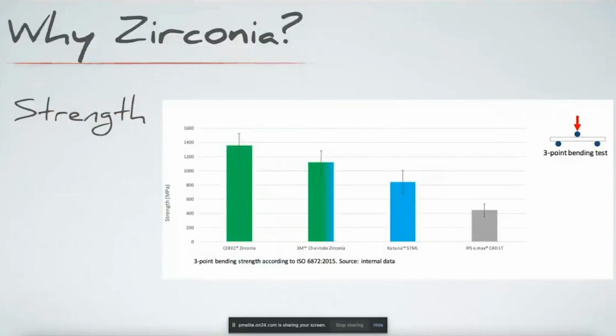And then as we make these zirconias a little more translucent, a little more aesthetic, we do start losing some of that strength. So you can see with 3M Chairside, we've taken a step down. We're a little below 1,200 megapascals. And when we go to Katana, we're somewhere in that 800 range. And with Emax, we probably are more in that kind of 450 to 500 range.